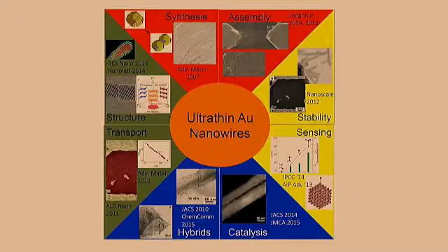So when we form gold at this particular length scale, less than 2 nanometers in diameter, I should also point out, the diameter of these nanowires is such that they are only like 5-6 atoms thick. These are really, really thin wires, okay? Which means that the surface is a significant part of the nanowire that we're talking about, right? We have done a lot of things. I'll just show you 2 examples to tell you how dramatically things change when we go to the nanoscale.